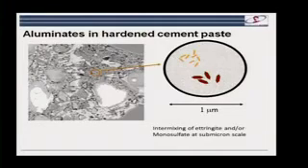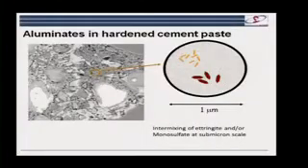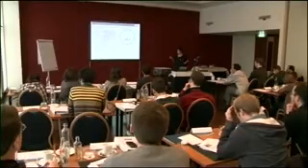And this can be seen quite nicely in the transmission electron microscope. The scanning electron microscope has lower resolution, and particularly when we try to analyze what this product is, when you make an analysis in the scanning electron microscope, as I'll show you this afternoon, you're actually analyzing quite a large volume, a volume of about 1 to 2 microns. So you can't separate these phases on the scale of microanalysis.